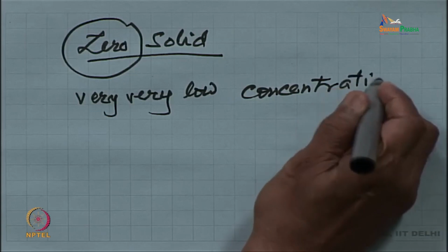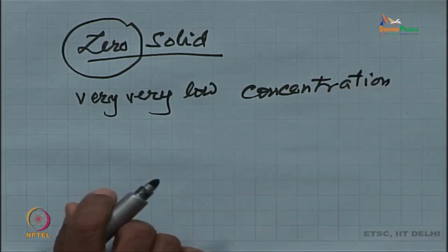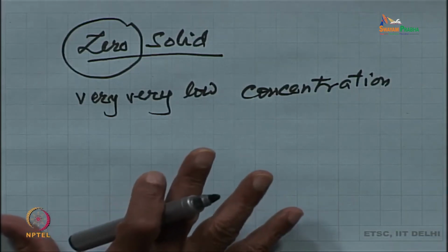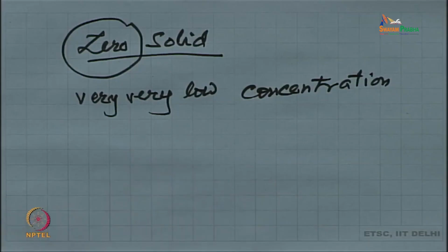So you have a very low concentration, low viscosity, and suddenly you add alkali, very high viscosity, and then when you wash, alkali is gone, viscosity is low, and even if it is trapped in the binder film, it would not change the tone and the brightness of the print. Okay?